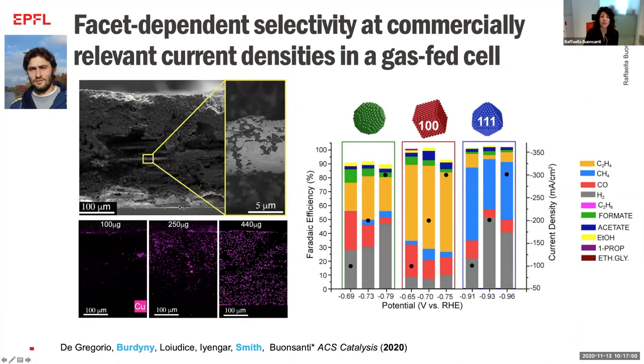So he basically was able to create this gas diffusion electrode, which integrates the copper catalyst. And we were able to verify that the intrinsic selectivity of this catalyst is still preserved in this different environment. It was especially key to observe the formation of methane, which we expected to be suppressed based on the highly alkaline conditions that develop in this type of cell.